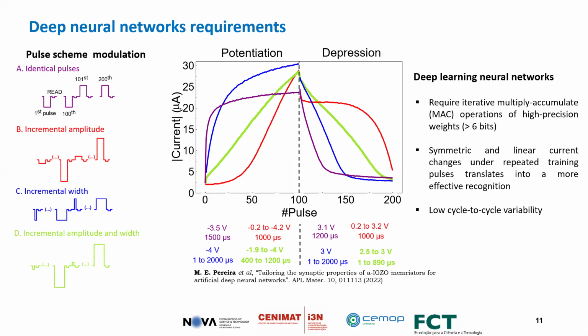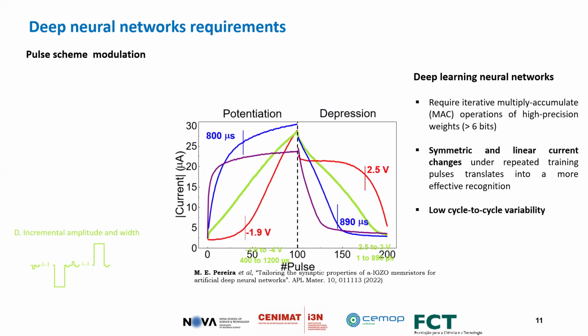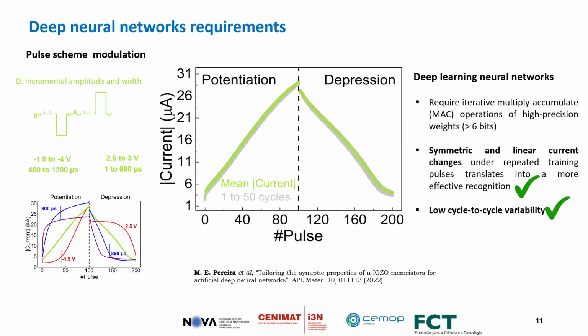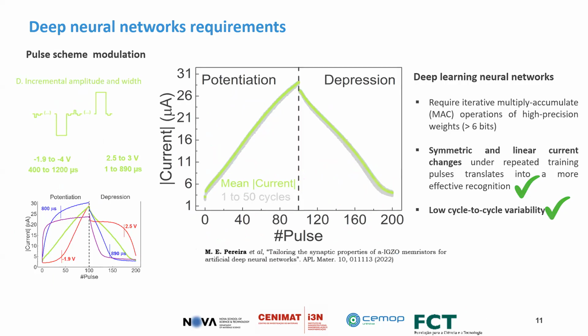And is it feasible to build a circuit based on that now? No, it's not, because if you want to change amplitude and width every time you want to adjust the weight, you need another memory system, another human system to remember, right? So this is achievable, but it's not feasible when you look at it at a system level. However, this is what we achieved, and we show that it is possible to really tune the devices, and at the same time with very low cycle-to-cycle variability.